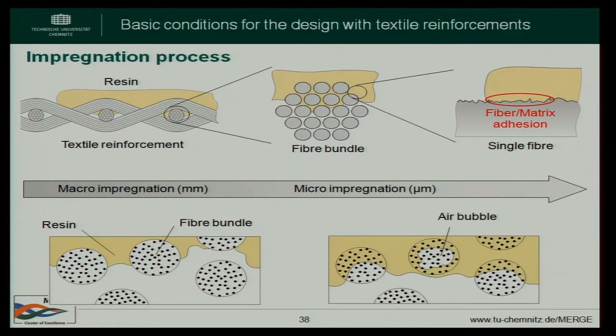The only thing you have really to ensure when you handle carbon fibers, as carbon fibers are electrically conductive, is that they don't get access to your control unit. This is a big problem using carbon fibers because of the electric conductivity. If you process carbon fibers, you get some fiber flying around, some small broken fibers. They should not go on your control unit, because if you get some contact, you get some electrical error, and it's more or less destroyed. So this is something you have to ensure.